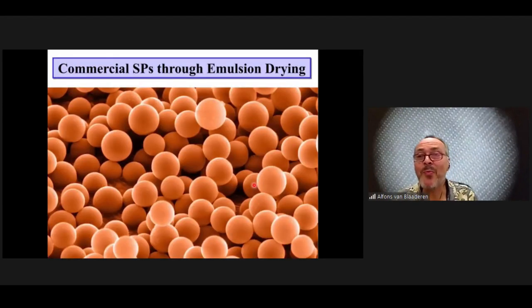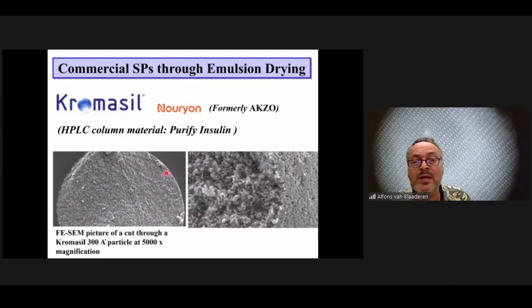This is my one example of superparticles with not equilibrium structures, but actually gel-like structures. But I did want to also mention in this Edwards Symposium that there is already a $1 billion market, I've been told, for supraparticles that are made on an industrial scale. So these are gel-like silica superparticles built up from very small silica nanoparticles that have also been made by drying emulsion droplets, but because there was salt added and the particles are polydisperse, we don't get beautiful crystals, but we get beautiful gels. It's all in the eye of the beholder, of course, what you want to get.